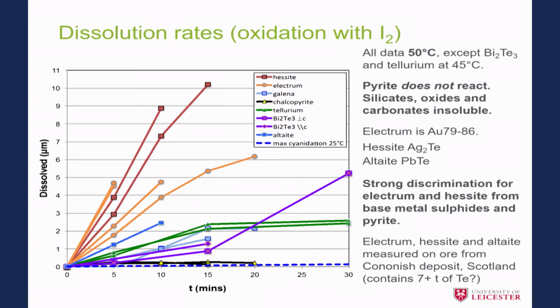Okay, so this is the data set that we had about 2 years ago now, where we had the leaching rate of various minerals, time against amount dissolved. So increasing slope here shows a faster rate of dissolution. Now remember our pyrite doesn't dissolve at all. Neither do your gangue minerals, silicates, most oxides, carbonates, and what we have here are our sulfide and telluride minerals. So starting at the bottom here, we have chalcopyrite, that hardly does anything, but bismuth telluride, we have galena, tellurium, that one's altaite, lead telluride, and then in orange here we have electrum, and here we have in red hessite, silver telluride.